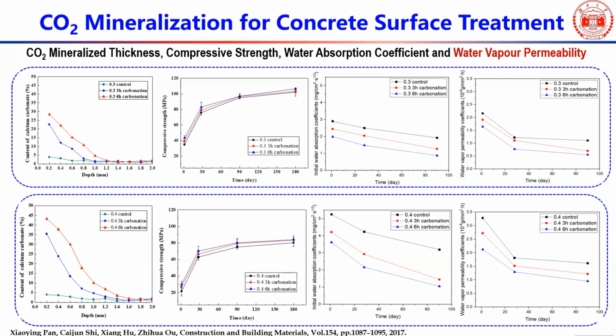So later on, when my students do some experiments, I have to ask them to ensure that from the surface to inside, from one side to the other side, it shows similar results. The same results. Otherwise, if you get a chunk, it's not a representative result. Right. And the second figure is the compressive strength. As we expected, because the carbonation thickness is very thin, very small, it only slightly increases the compressive strength.